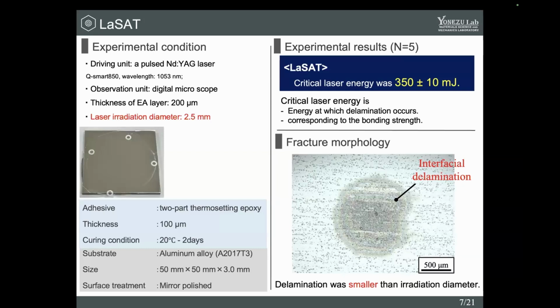In LASAT, we determine the critical laser energy. Critical laser energy is the minimum laser energy generating delamination, and it corresponds to the bonding strength. As a result, we determined the critical laser energy was 350 millijoule. And at this energy, we observed interfacial delamination as shown in this figure.